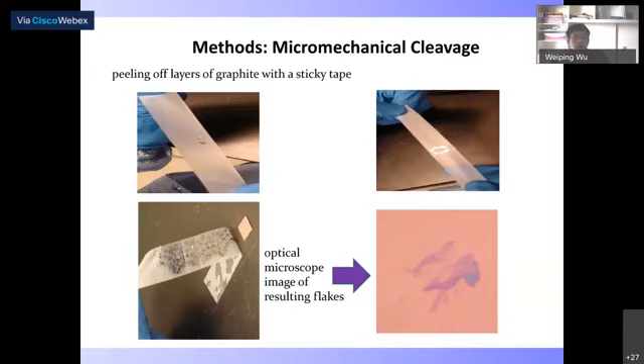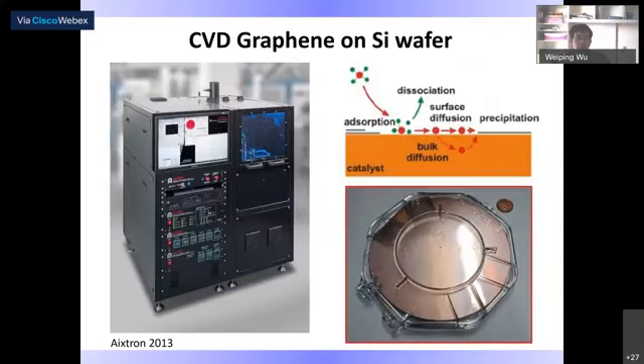Let's have a comparison with mechanical cleavage, using very simple technology and tools like graphite and tape. What you can get using this very simple process is a very small area of graphene. Although the quality is quite high, the size is usually tens or hundreds of microns, so you can only find them under the microscope. These samples are quite nice for fabricating high performance devices. But this process is not controllable, so you can't really get very high quality, large area, uniform graphene material. So there are efforts on growing graphene at the wafer scale.